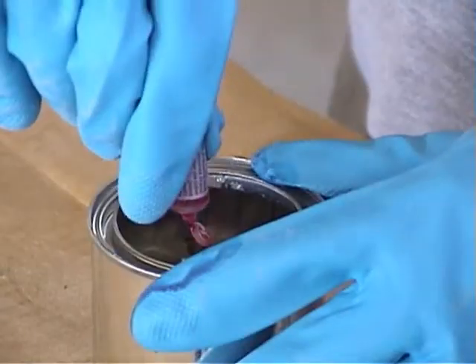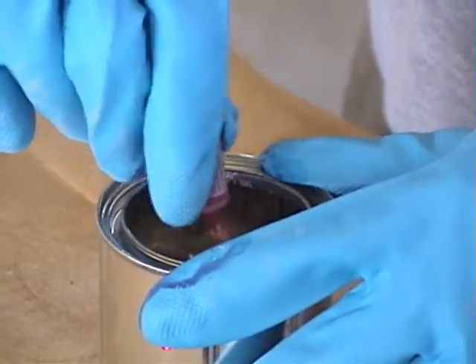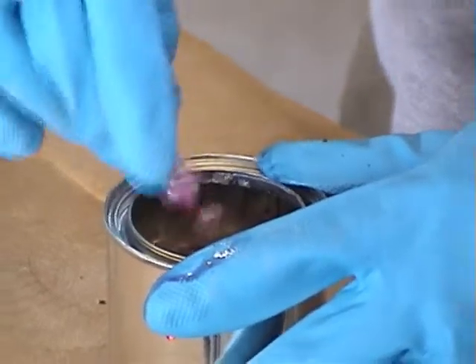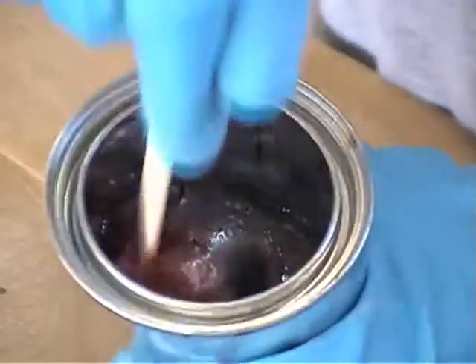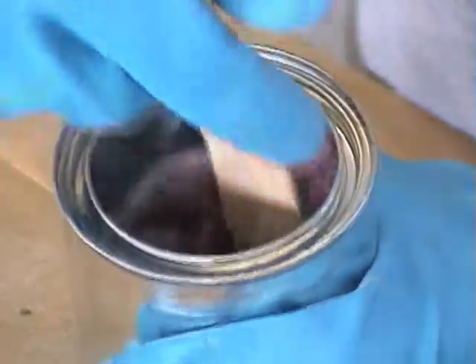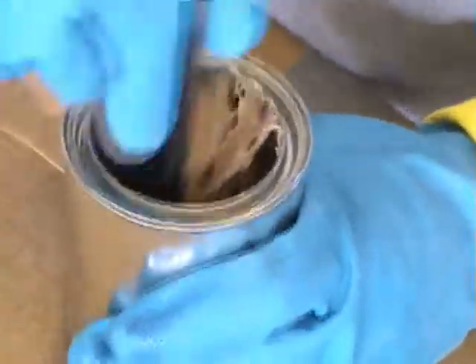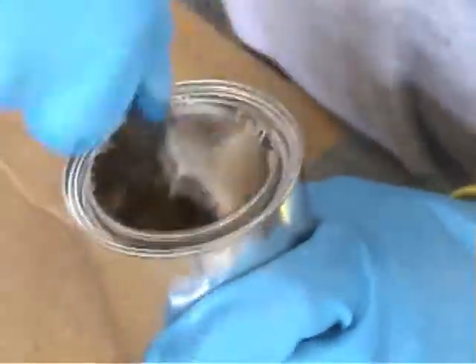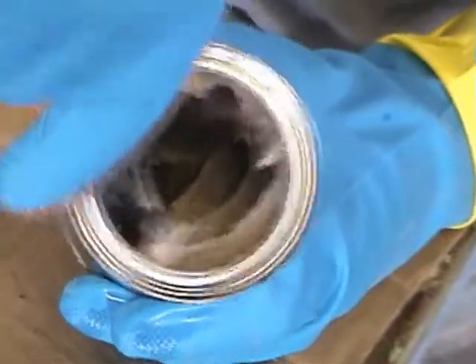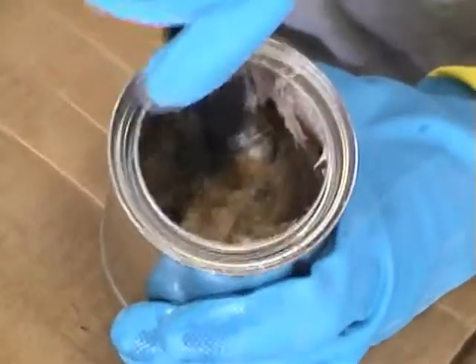Make sure you're wearing impermeable gloves and chemical splash goggles. Then add the catalyst to the adhesive. The catalyst is red. The way you know when the adhesive is mixed thoroughly is when the color is consistent throughout. Be sure to scrape the sides and bottom of the can while mixing. We have a consistent color. Now we're ready to coat the cut ends of the pipe.